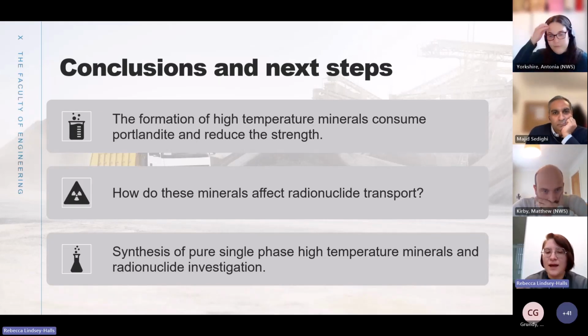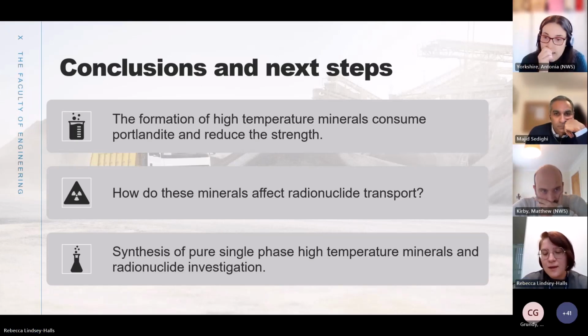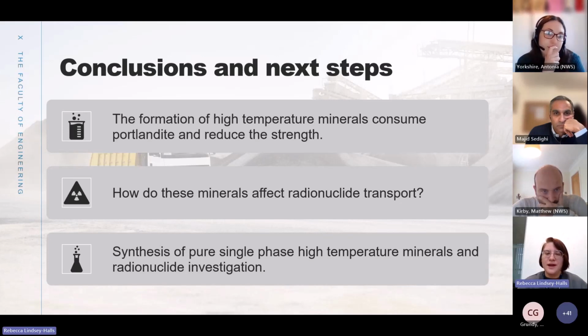But then the next question is, how are these actually affecting the radionuclide transport? So I'm going to synthesize pure single phase minerals and then actually see what happens when I mix them with radionuclides. Because if you're losing the portlandite and you're losing a bit of that pH stability, but you instead have this gamma C2S phase that's absolutely brilliant at sucking up radioactive carbon, could you adapt the formula so that you get both?